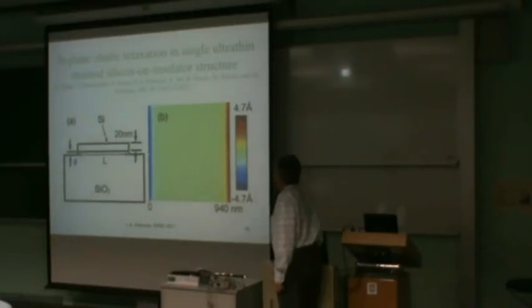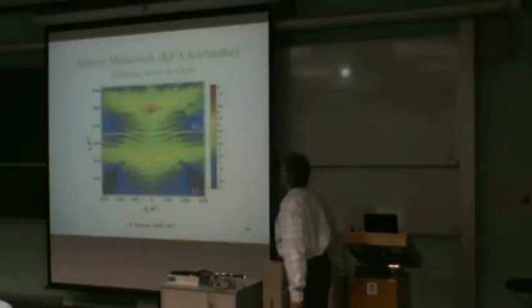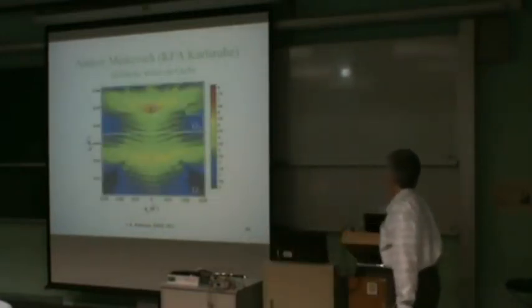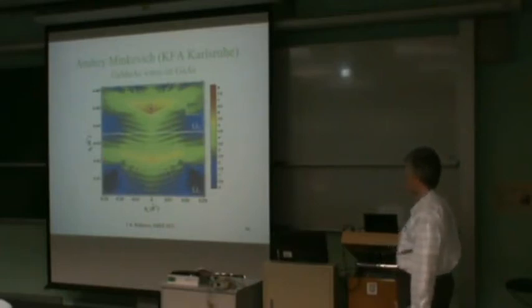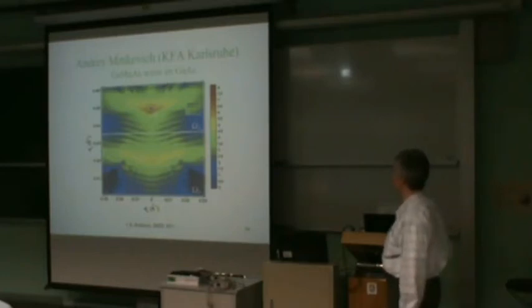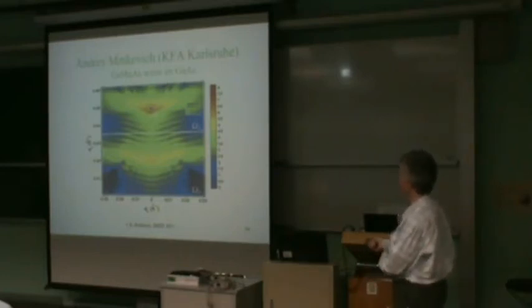That shows the same thing. Okay, so this is a different material, but it's the same kind of measurement done by a different group. This is Andrei Minkovich in Karlsruhe looking at wires of gallium manganese arsenide and gallium arsenide. And here he's got measurements of both the gallium arsenide peak and the gallium manganese arsenide peak.